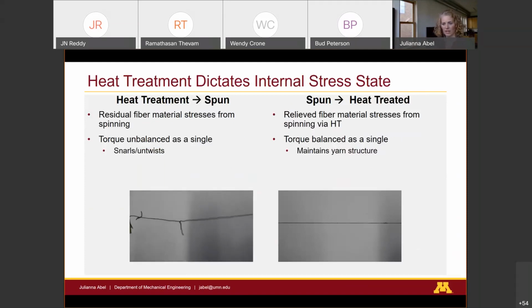And so when we want to use these as actuators, they provide a lot of twisting motion. If we spin it and then heat treat it, we're removing those stresses, and we create a torque balanced structure that's really easy to work with using traditional manufacturing equipment. You can see as this one is held slack, it just drops, and there's no pigtailing.